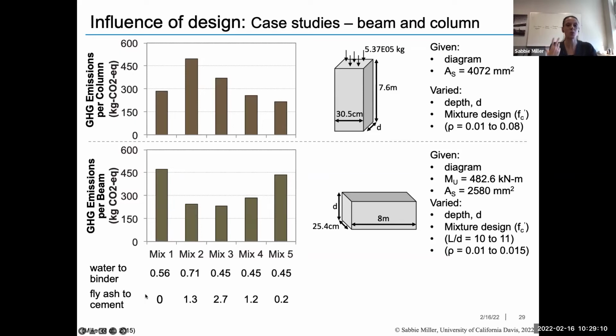And what's interesting is what we would specify in terms of a desirable concrete mixture to minimize environmental burdens for a beam, mixture 2 or 3, actually leads to a pretty high emissions mixture for the concrete column. And this is associated with how the strength of the materials play into the volume of material actually necessary, as well as the role of the reinforcement on the overall cross-section of the member necessary. And we see that if we wanted to lower burdens across multiple members for a variety of loading conditions, we actually might have to compromise and not choose the lowest emissions material for any given single member, but rather try to analyze an entire system cumulatively to pick a material that will lower overall burdens.